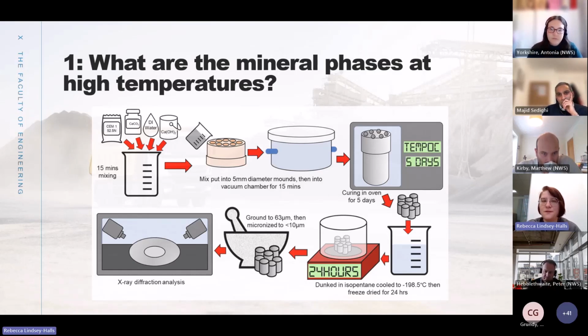They're then put into a vacuum chamber for 15 minutes. This is to remove any artificial porosity that you might get, so you're not getting any air bubbles inside. They're then cured for 5 days at whatever temperature you want to look at. They're then carefully removed. These cores are then dunked in isopentane that's cooled using liquid nitrogen. They're then freeze dried for 24 hours and weighed before and after to make sure that they're losing their pore water. This is to arrest the hydration so that the minerals you're getting out don't continue to evolve and develop, so it is representative of that time point. They're then ground to a particle size of less than 10 micrometers before being measured using X-ray diffraction. They're ground to be very small so that you get a proportional measure with the X-ray beam.